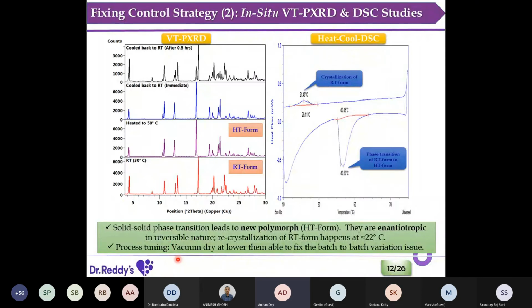If after precipitation of the material we vacuum dry at lower temperature, lower temperature meaning far below 43 degrees, there won't be any phase transition. In that sense we can get reproducible batches, and it clicked and it happened. In that way the process was developed, and we filed the DMFs and all this. That's the thing.